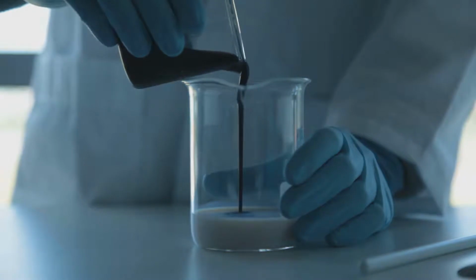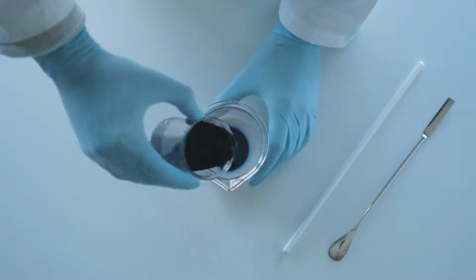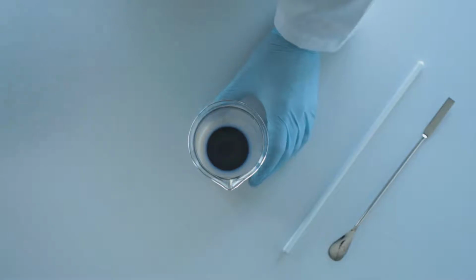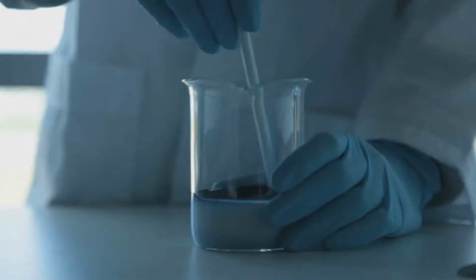Nanomaterials can provide textiles with new functionalities that allow them to respond to external stimuli in a totally surprising way. CTAG, within the CarbonInspired 2.0 project, has developed a prototype of heating material that demonstrates the enormous advantages obtained with the addition of a tiny amount of nanoparticles. For this prototype, a textile substrate has been embedded in a resin with nanoparticles and several additives. The prototype has shown a temperature increment within the range from 15 to 50 degrees Celsius and even higher, working with security voltages.